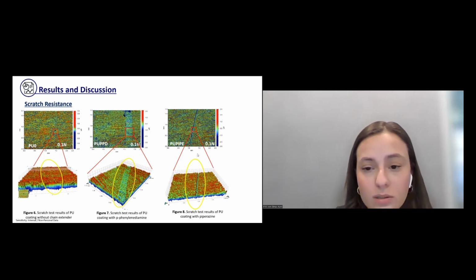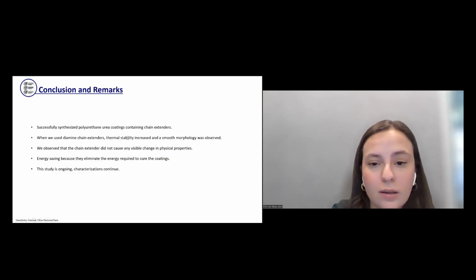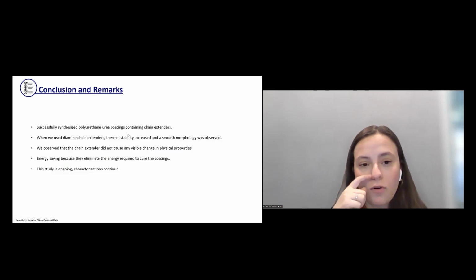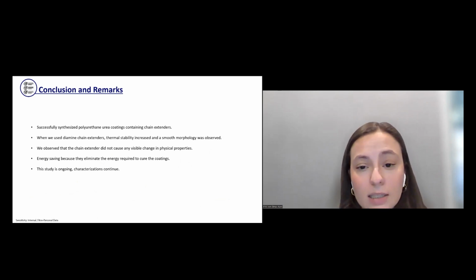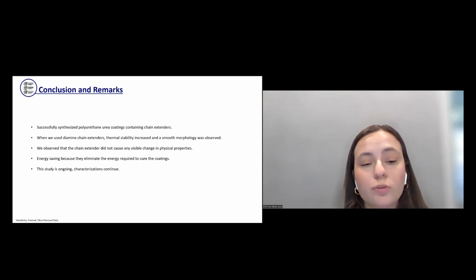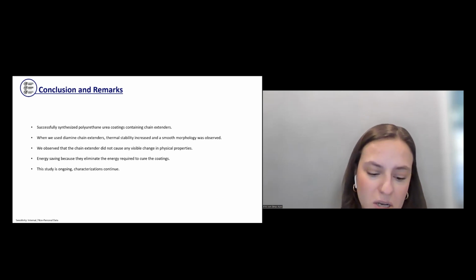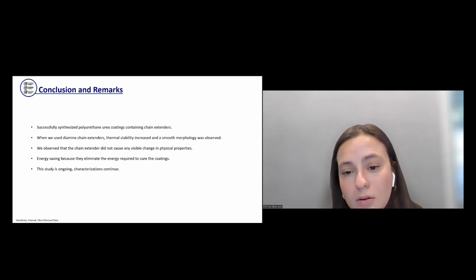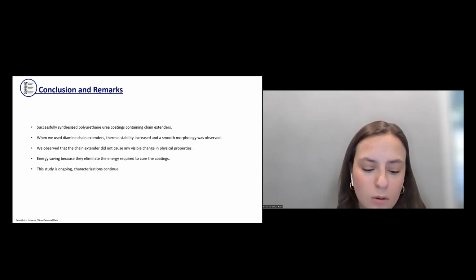In the coating containing piperazine chain extender, the cross-linking is more than the blank one, but less than the diamine one, so the scratches are of medium depth. Last of all, we have successfully synthesized polyurethane coatings containing chain extender, and as a result of the tests, we observed that when we use diamine chain extender, thermal stability increased and smooth morphology was observed.